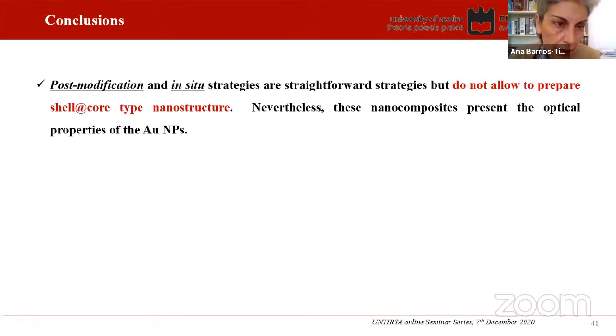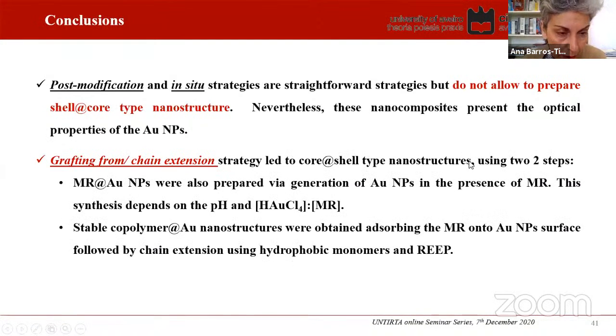So, as a few conclusions of this work, we can realize that post-modification and in situ strategies are actually very straightforward techniques or strategies, but do not allow to prepare core-shell type nanostructures. As I showed you in the early slides, we had just aggregates of particles and then patches of polymer, so not really well controlled core-shell nanostructures. Nevertheless, the nanocomposites, if you can call them that, because they are a mixture of two phases anyway, presented the optical properties of the gold nanoparticles, so they may be used for other applications.